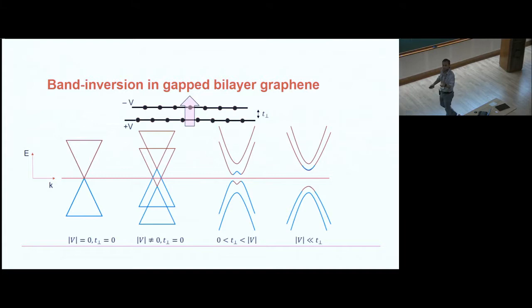Then I start turning on the interaction between the two layers with a hopping integral of t perpendicular. And then you see that there will be a parabolic band; the bands in bilayer graphene are parabolic, at least at large distances. And then you have a little bit of the conduction band of the valence band of the lower layer sticking to this over here. So this is now a very similar situation. If you apply a very large coupling, then you go in this direction, but experimentally in real systems, we mostly deal with this situation where a band inversion has occurred in bilayer graphene in the presence of a strong electric field and interlayer coupling.